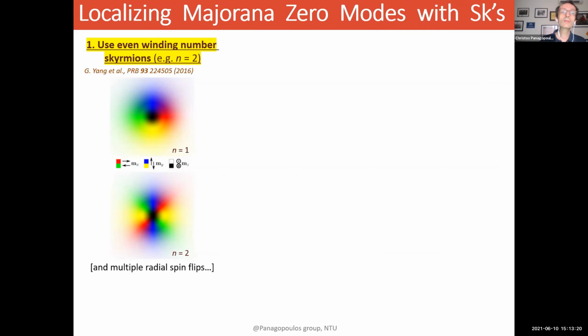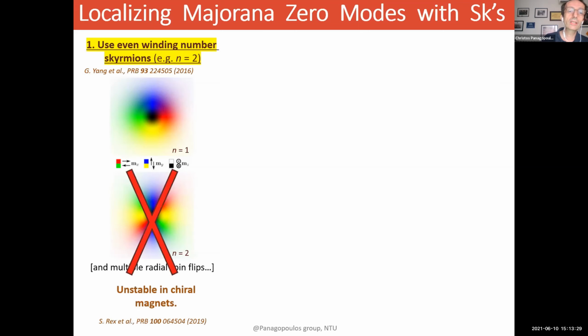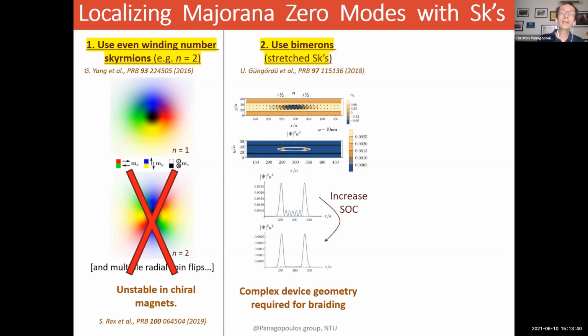Now, if you have an even winding number in skyrmions, such as n equals 2, for instance, it has been suggested that one could look for a radial spin flip that could localize Majorana zero modes. The problem in practice is that they are unstable in chiral magnets. Another possibility for localizing Majorana zero modes with skyrmions is to use bimerons. These are essentially stretched skyrmions, such as shown here. And here is a bimeron, for example.